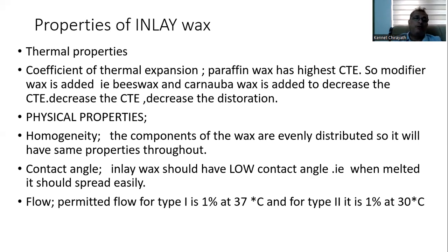The flow permits 1% at 37 degrees centigrade for type 1, and for type 2, 1% at 30 degrees centigrade. So it is a permissible flow of the inlay wax in the prepared cavity. The flow of the inlay wax primarily depends upon the body temperature.